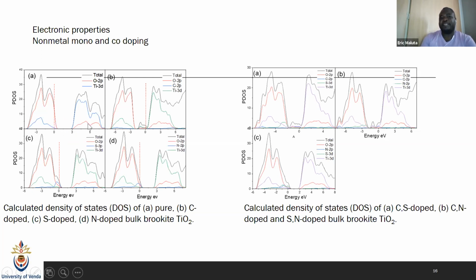We can just look at the band gap, but then when we dope it with carbon, we can see that, due to the foreign element which has been introduced, we were also able to have some activity, or the introduction of more bands, between the band gap. And now we also reduce the band gap, which is what we wanted to achieve, because this means that if we reduce this big band gap and introduce more bands here, then our surface or the bulk structure will now be able to be active in the visible region and towards the near infrared.